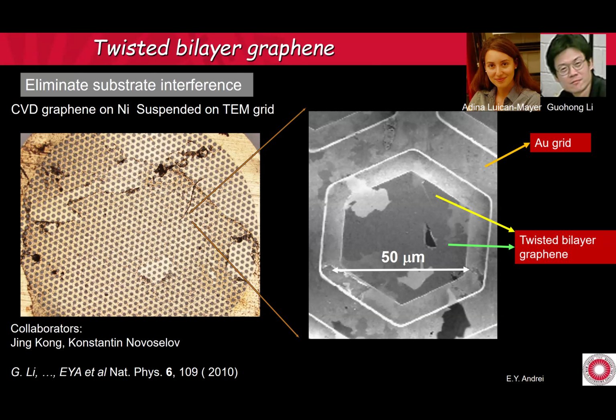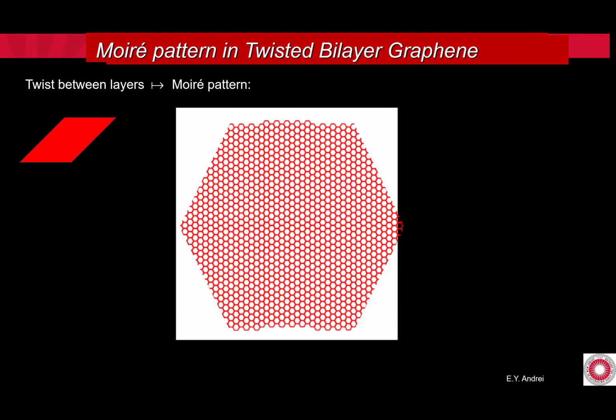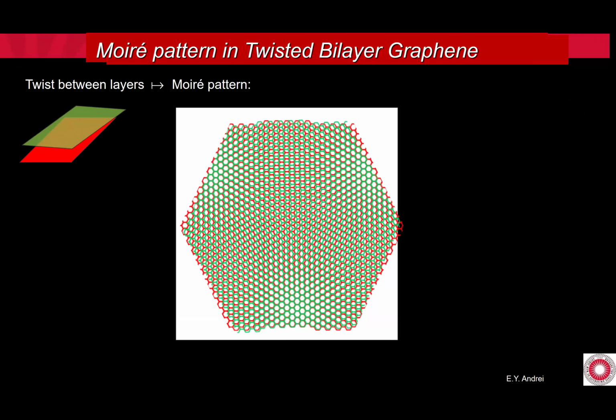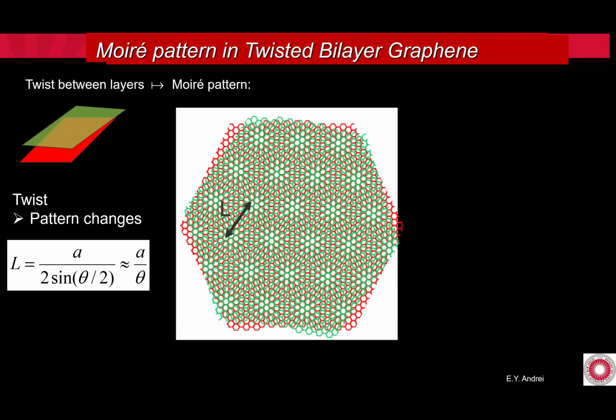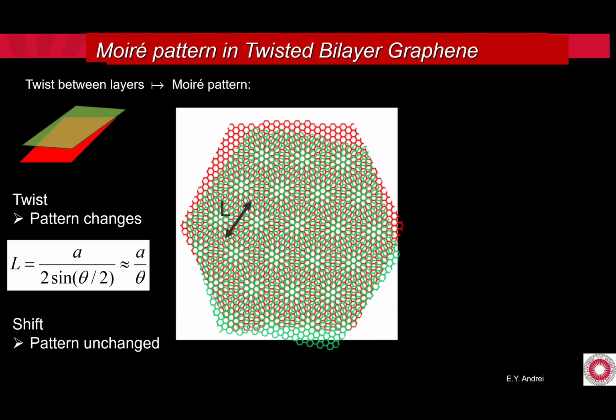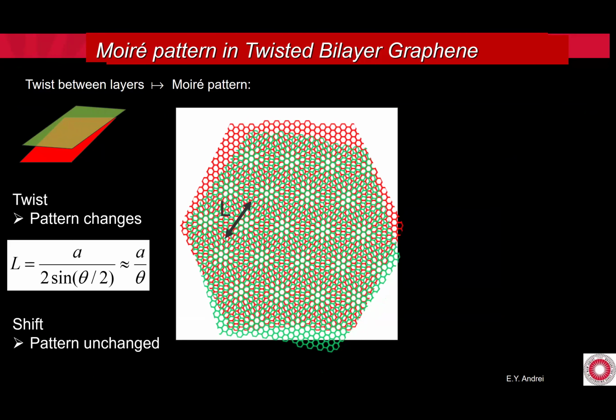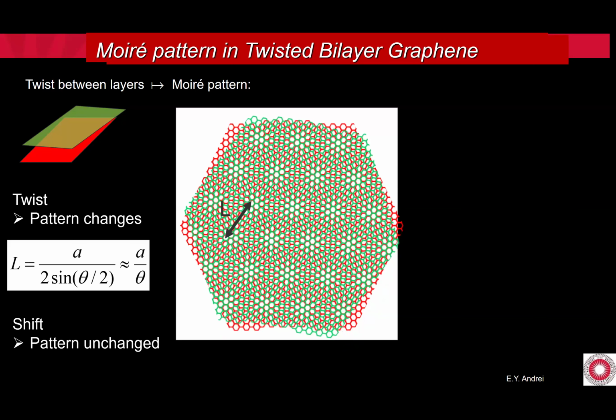So now we could come in with the STM and look at it. Just to show you what happens: okay, you've seen this a million times. This is the Moire lattice. The size is inversely proportional to the twist angle. A is the lattice constant. One interesting thing about this, to which I'm going to come back later, as an experimentalist, this is extremely robust because I don't care how the layers are aligned. If I have a shift, you see the pattern doesn't change with the shift. So I don't have to worry about aligning it. This is very useful, as you'll see later.